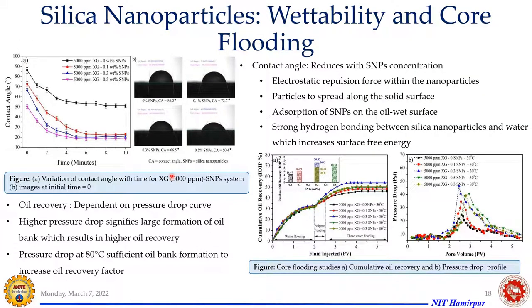And as usual, with nanoparticles, as I was telling you, there is some disjoining pressure. So we have seen how the wedge film was formed. In the introduction slides, we have already seen how the wedge film was formed and how it was taken out to the surface, at the very beginning. So here we have taken these same nanoparticles and tried to check the wettability. Initially we have only polymer. The contact angle was around 85, 86. Then it came to around 54, 55, like 50 plus.